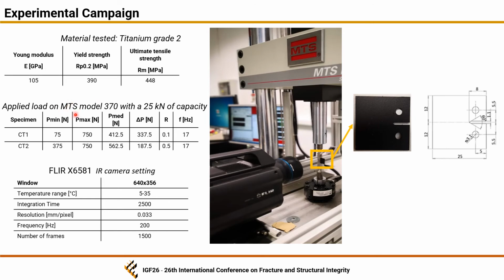The test material was a titanium grade 2 small scale compact tension sample tested at an MTS loading frame with a 25 kilonewton capacity. The loading condition involved a stress ratio of 0.1 and 0.5. The thermal acquisitions were carried out by using a FLIR X6581 infrared camera that acquired 1500 frames at 200 Hz.